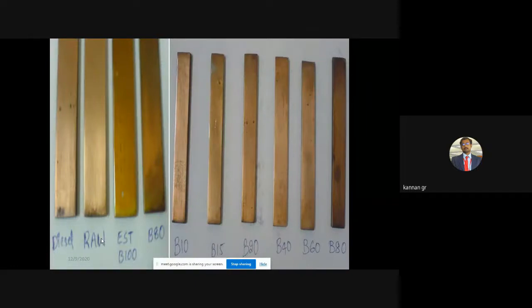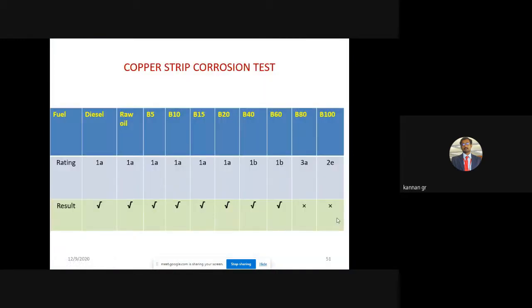Here, after the copper strip corrosion test, for my test fuels: diesel, there is no change; raw palm oil, there is no change; esterified B100, a biodiesel, there is no change. That means almost the 3A category, and B80 also 3A category, the dark tarnish type. Then B10, B15, B20, B40, B60, B80, there is no change. B80 and B100 may show slight blackish color. That may be within 3A. Yes, that may be tabulated.